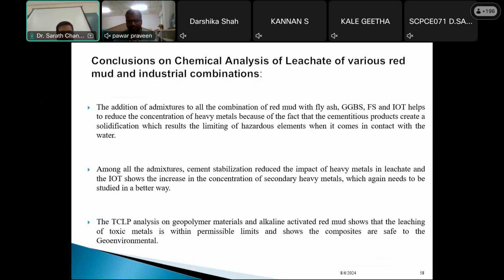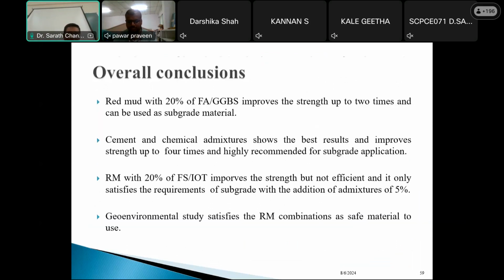The TCLP analysis on geopolymer materials and alkali-activated red mud shows that the leaching of toxic metals is within the permissible limits and shows the composite is safe. The overall conclusions: red mud with 20% of fly ash and GGBS increases the strength up to 2 times, and it can be used as subgrade material. Cement and chemical admixtures show the best results and improve strength up to 4 times, and are highly recommended for subgrade application. Red mud with 20% foundry sand or IOT improves the strength but is not efficient, and only satisfies the requirements of subgrade with additional admixtures of 5%. The geo-environmental study shows the red mud formulations are safe materials to use.